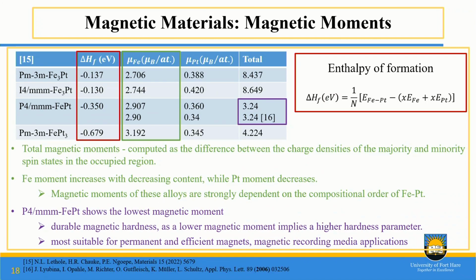So we went on to test their thermodynamic stabilities by calculating the enthalpies of formation. We find that the enthalpies of formation are negative, which shows good stability. Then we went on to calculate the magnetic moments just to determine how magnetic they are. We see that they have various magnetic moments, and the magnetic moment of the equiatomic composition, which is FePt, we find that it was in very good agreement with what has been found experimentally. So it means that our approach was able to reproduce what has been found experimentally.